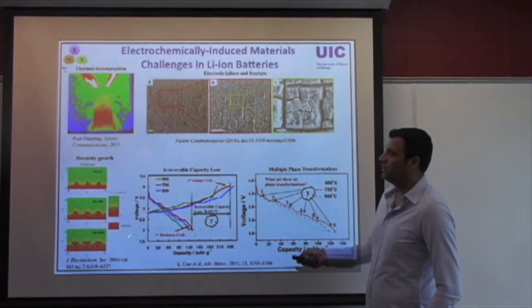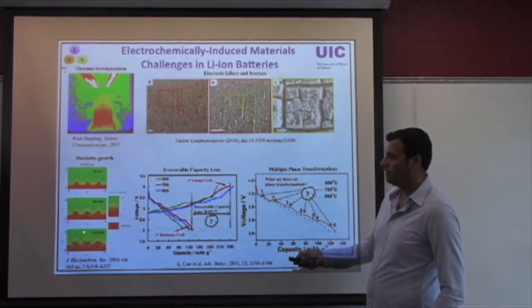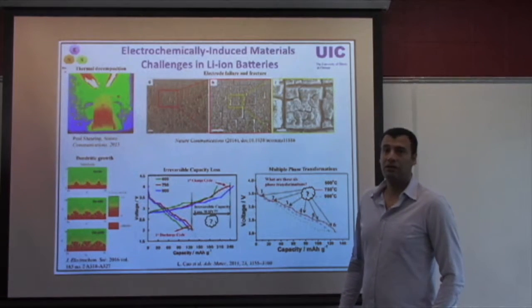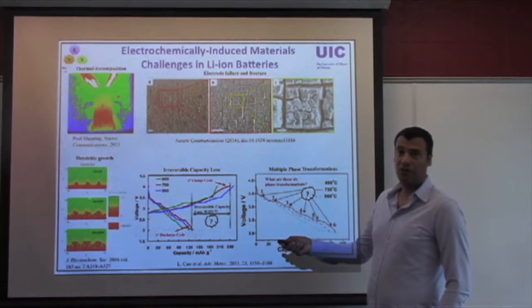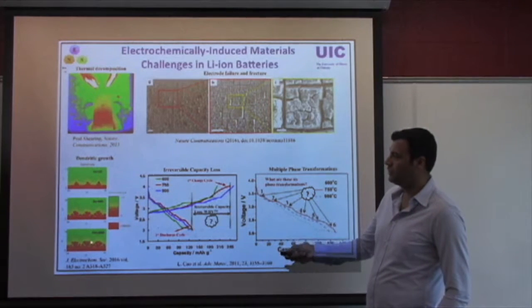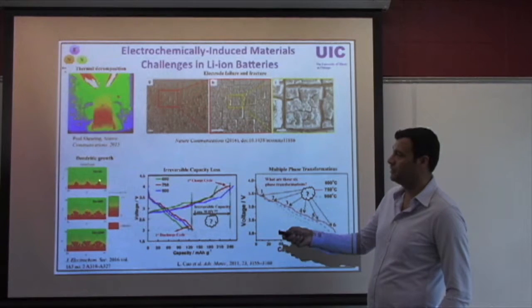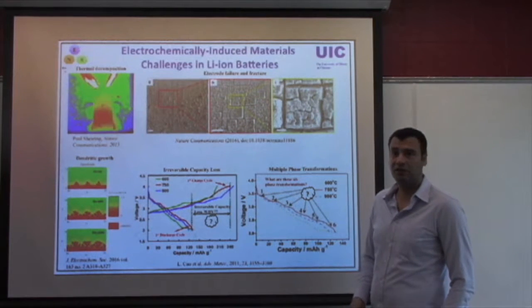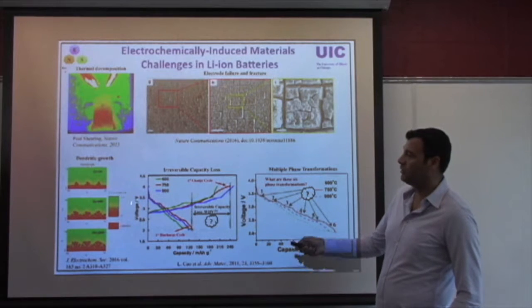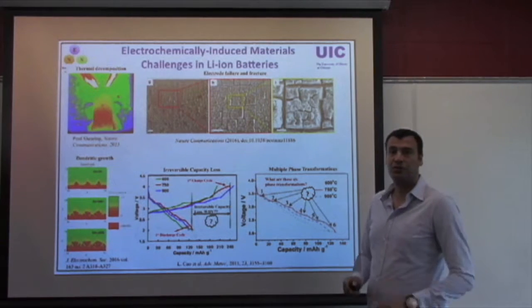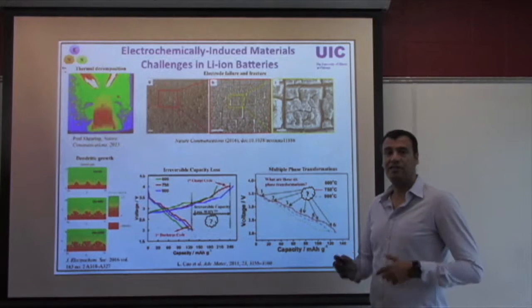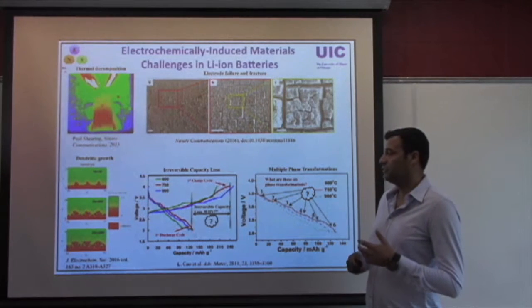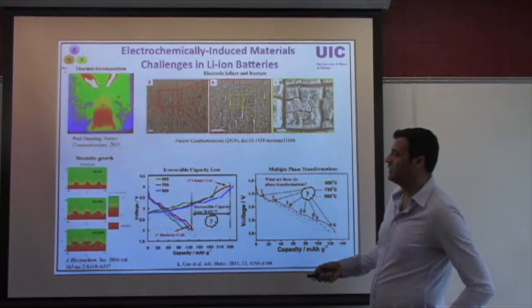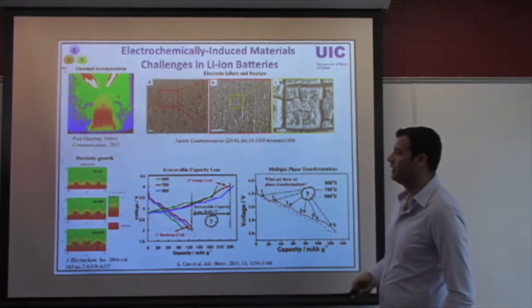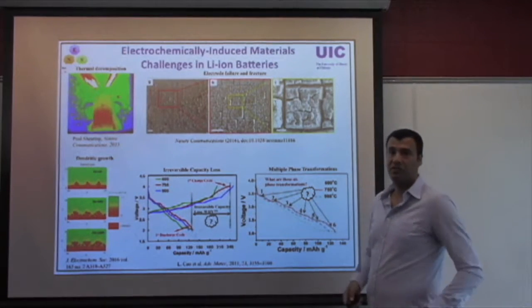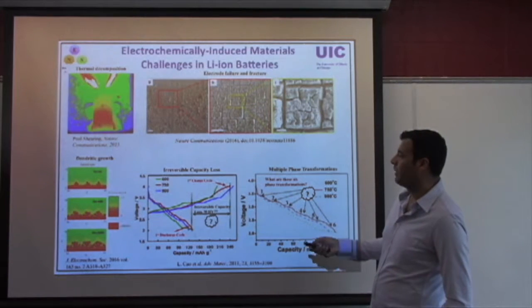Another sort of failure issue that we face in these systems is dendritic growth of lithium, which this work is trying to simulate and model. It involves some sort of interplay between SEI formation and the electrodeposition of the lithium on the electrodes, which eventually might result in the failure of our energy system.